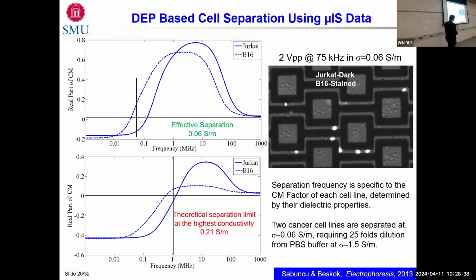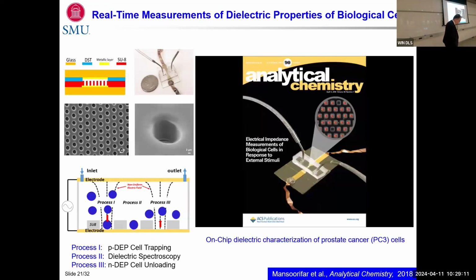And we did these experiments, and we were trying to find, can we do it at that conductivity? Theoretically, we can go as low as this, but that conductivity is really giving you a very minor Clausius-Mossotti factor. And if you just increase the electric field, you have other effects that you're dealing with, and it didn't work. Well, that's fine, 0.06 Siemens per meter, but the problem is that you need a 25-fold dilution for this to work, and it's not a good idea. So we have shown something that's semi-useful.